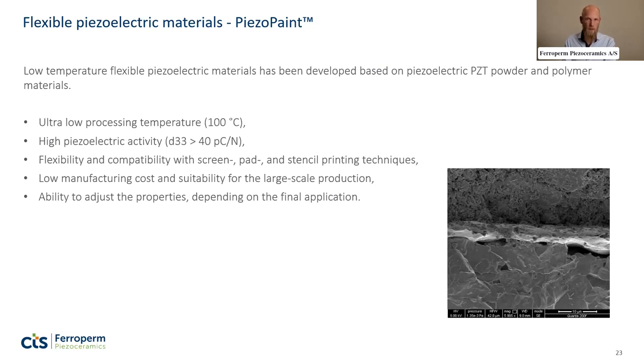So the sensitivity that we're achieving with this is a D33 of around 40 picocoulombs per Newton. And it depends a little bit on the processing. We have different approaches there, but this is the order of magnitude that we're seeing. It's still enough to enable some of the applications that we had in mind.